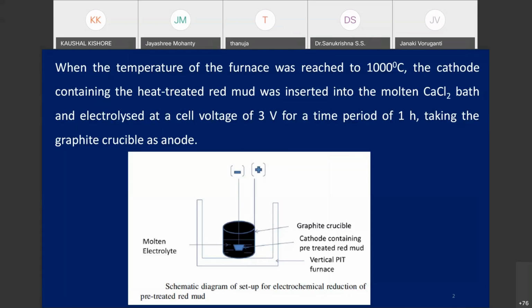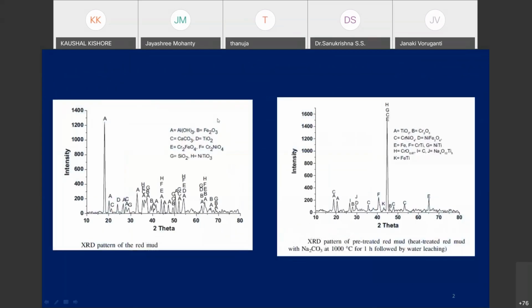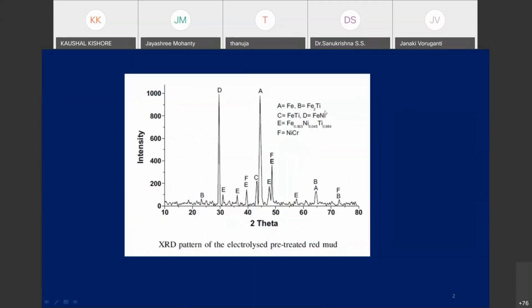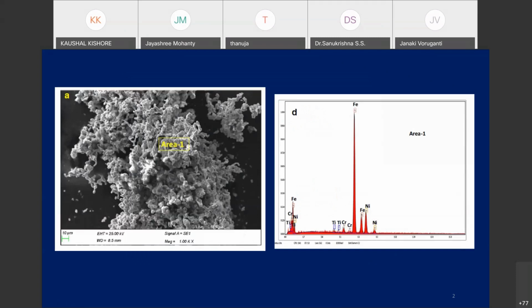Usually you prefer to do it at 900 to 950, but here, specifically for a typical experiment, it is 1000 degrees centigrade. So after electrolysis, you can see here the actual red mud XRD phase analysis. After the heat treatment, some metallization of iron metal had happened, but after electrolysis, you can see the material phases you have analyzed. This is mostly Fe, Fe2Ti, FeTi, FeNi, NiCr and likewise. So various phases we observe show that titanium, nickel, chromium are present in the material.